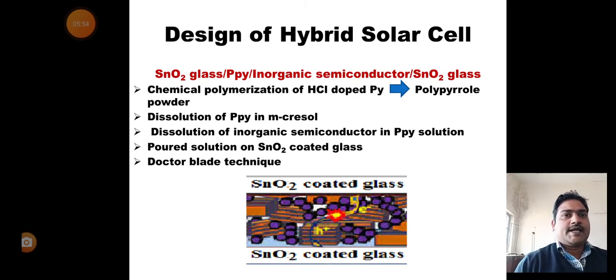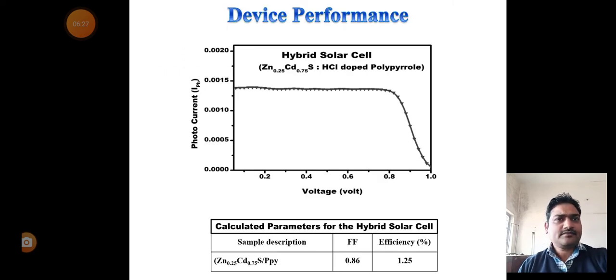Due to the applicability of as-synthesized zinc cadmium sulfide sample, I have designed a hybrid solar cell using polypyrrole p-type semiconductor. The polymerization step and method are shown here in this table. Also the prepared polypyrrole semiconductor and n-type inorganic zinc cadmium sulfide sample have been used to design the hybrid solar cell by using the doctor blade technique. The device performance is shown here in this slide.